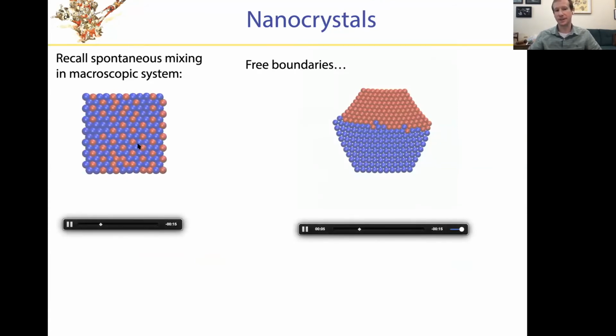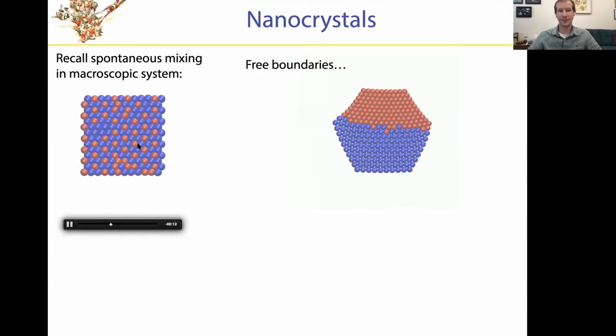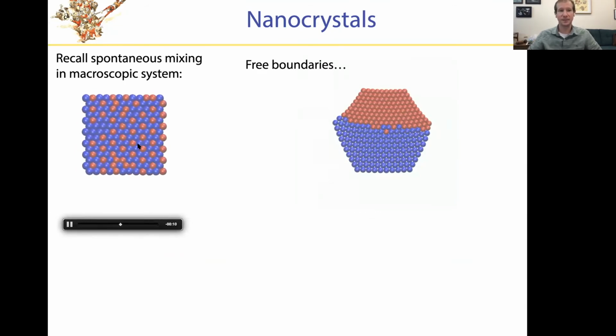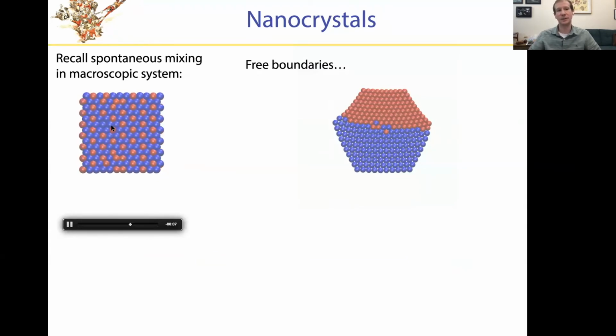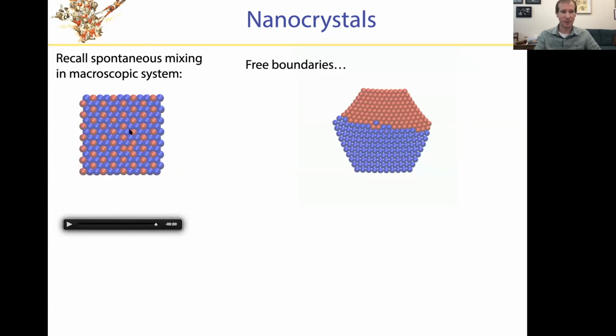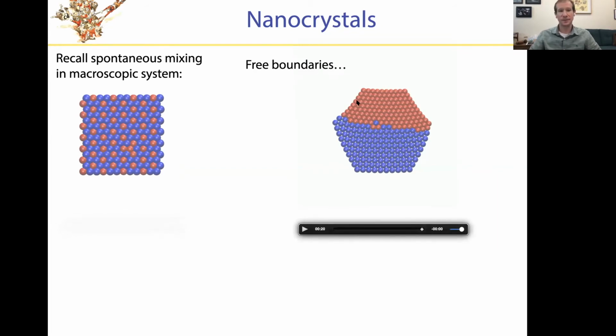Firstly, I need to note that the results that I've shown you so far, those movies and those phase diagrams, pertain to macroscopic systems. Even though these little simulations I'm showing you involve just on the order of 100 atoms, we've used a trick here. The trick is to take this part of the system and repeat it periodically above and below, left and right, to give it the impression that it's surrounded by a bulk environment. Here I'm considering instead a nanoparticle, something that doesn't have this continuation, and something that has then free boundaries in a way that this macroscopic system simulation did not.